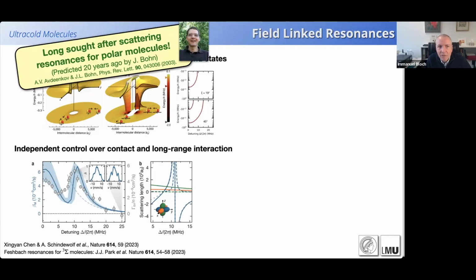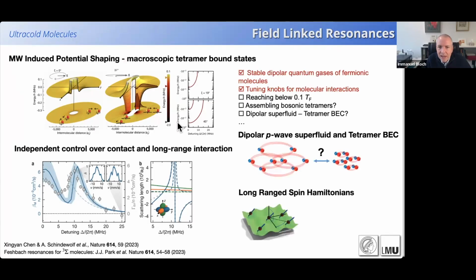They were first predicted by John Bohn in the field, and we've been able to detect these field-linked resonances with these ultracold polar molecules directly in our system by just changing the ellipticity of the microwave field. And in contrast, maybe, to some of you who know Feshbach resonances, where in atoms you basically have to be lucky to get one, this is a universal technique, I think, that should apply to any polar molecule that you can have in the system. Now, why is this interesting?